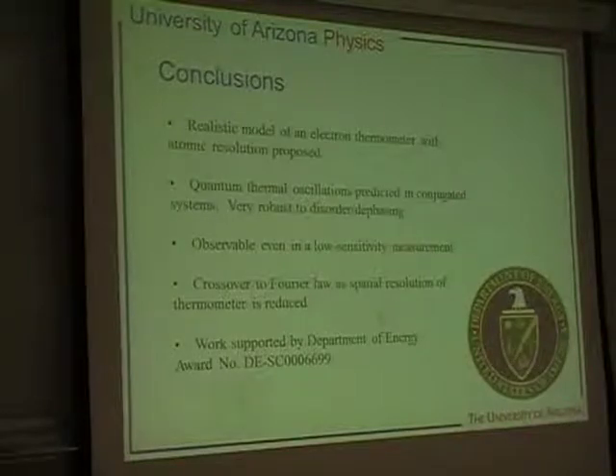To summarize what we've done, we've come up with a realistic model of an electron thermometer with atomic resolution, or at least proposed one. We can predict quantum thermal oscillations in all kinds of conjugated systems, from individual molecules to graphene. And we've argued, importantly, that these quantum thermal oscillations are extremely robust with respect to disorder and dephasing. There's basically no getting rid of them. We've also shown that they are still observable in a low sensitivity measurement, which is where the current STHM technology is. And we've explained the crossover to the classical thermal conduction mechanisms as being really understandable only in terms of